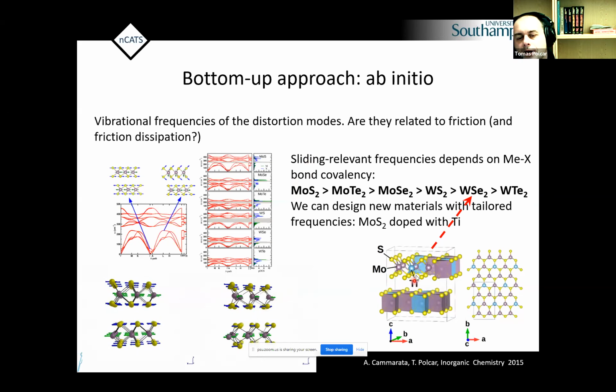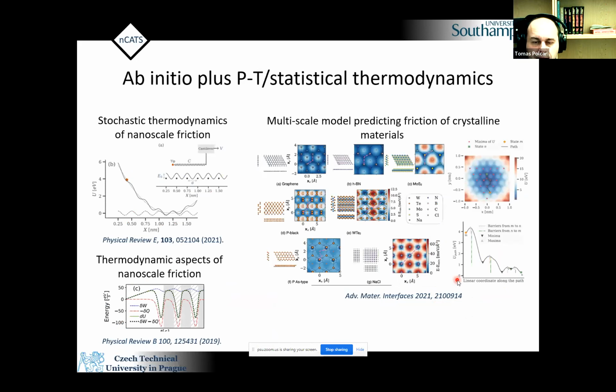So he proposed titanium, for example, and calculated. This is just an example here, because we published papers sometimes after that showing that very likely there is no such compound like molybdenum titanium sulfur at normal conditions. But as a concept, I think it's very interesting work. And then finally, to add, but I will not spend much time on that, we combine this ab initio, because we have the potential energy surface, with the standard Prandtl-Tomlinson model or statistical thermodynamics to understand really nanoscale friction of purely crystalline materials. And I have to say as well, in this case, ideal materials, no defects and so on. We can discuss it later.